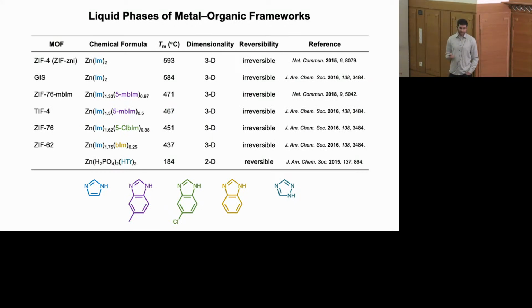And so this table shows all of the examples of 3-dimensional metal organic frameworks that can undergo a transition from a crystalline solid phase to a molten liquid phase. And what you'll notice is that there's very little structural and chemical diversity within these lists. So these are all almost exclusively zinc azolate based framework materials that undergo melting transitions at very high temperatures that are actually irreversible. So a lot of these materials start to decompose immediately once they're in the liquid state.